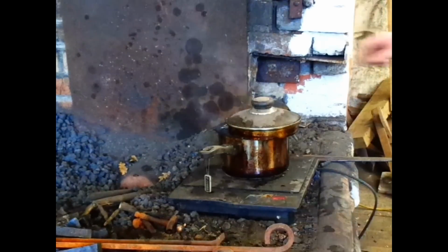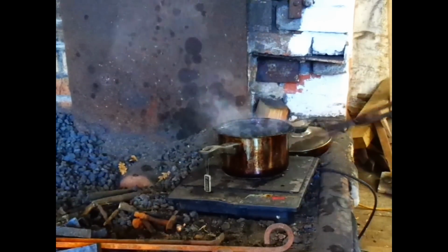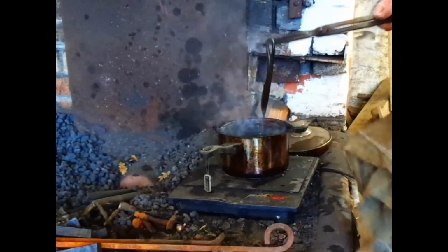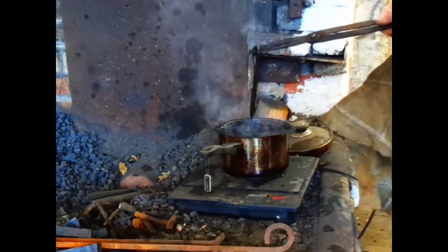After the second normalizing cycle, I heat the blade again, making sure to have an even heat. I test the blade for magnetism and then quench it in the warm oil. Again, I make sure to move the blade up and down in order to prevent the bubble shield. The blade is then placed in the tempering bath at 220 centigrade for 2 hours. I repeat this process twice in order to make sure that all the grain is allowed to shrink. After both tempers, the blade is allowed to air cool.